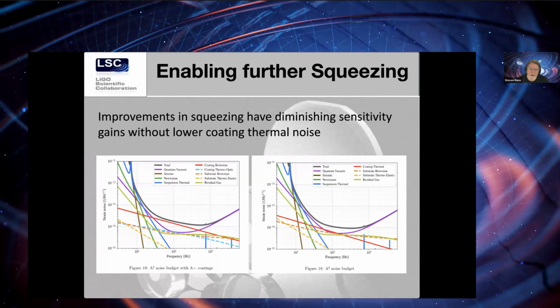And as Bram also mentioned, the 2 big improvements that are happening in the central noise bucket for LIGO are reducing the coating thermal noise and increasing the squeezing. Now, squeezing is a great technology, but if you don't pair that with a decrease in the coating thermal noise, then a lot of the benefit from the squeezing is lost. As you can see here, if you cannot lower the coating thermal noise, then you can't bring down the sensitivity even in areas where the squeezing curve is low. So in order to take full advantage of squeezing, we need the lower coating thermal noise. And the only coating that can provide that thus far is AlGaAs crystalline coatings.